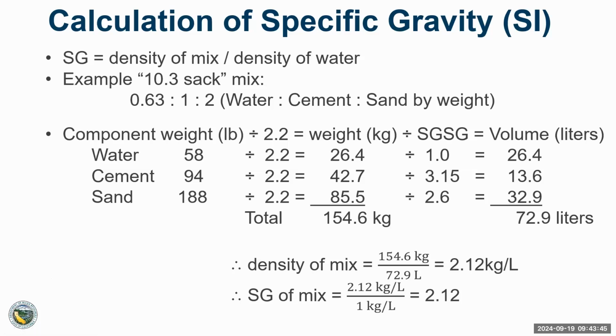And believe me, even though you're dealing with kilograms and liters and so on, it is just so easy. It is very easy in metric. So just walking through this slide a little bit, the third bullet there is a typical grout, your 10.3 sack mix. So it would include for one bag of cement, which is 94 pounds, 58 pounds of water and 188 pounds of sand. Now, as you know, we convert pounds to kilograms by dividing by 2.2. So then that one bag mix, if you like, weighs 155 kilograms approximately.